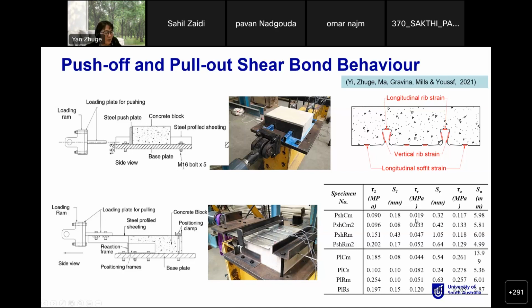And this is for the pull out. This is push in, and this is push off, and this is pull out. And again, the pull out results are also similar, similar as well for the ultimate bonding stress. Okay. And finally, S1 is the end slip and the maximum chemical bond. SR is the end slip and the residual bond. And SU is the end slip and ultimate bond. So you can see all the performance is kind of consistent for the push off test, but there are some issues for the pull out test here for these deformations.